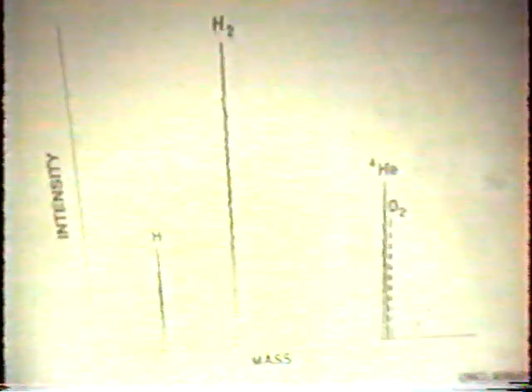So to really try to define helium in a huge quantity of deuterium gas, you have to try to separate the deuterium gas out first. And we did this by passing it through a cryofilter, activated charcoal at liquid nitrogen temperature. We found one filter process was not enough. Some deuterium still got through, so we passed it through a second thinner filter, which really acted like a gas chromatography column. It slowed down the flow of any deuterium, so it got through slower. But by the time it passed through the second filter, pretty much all the deuterium was removed, and only the helium was getting through.